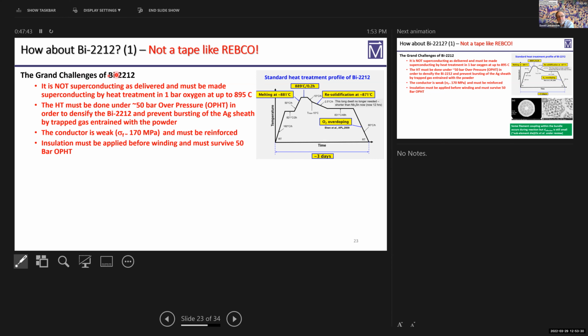wanted to go back to bismuth 2212. But the grand challenge is it's not superconducting as delivered. And so we must take responsibility for making it superconducting by heat treatment. We have to do that in 1 bar of oxygen. We actually have to melt the bismuth 2212 inside a silver tube. And so we actually go up to about 890 degrees centigrade, typically 889.